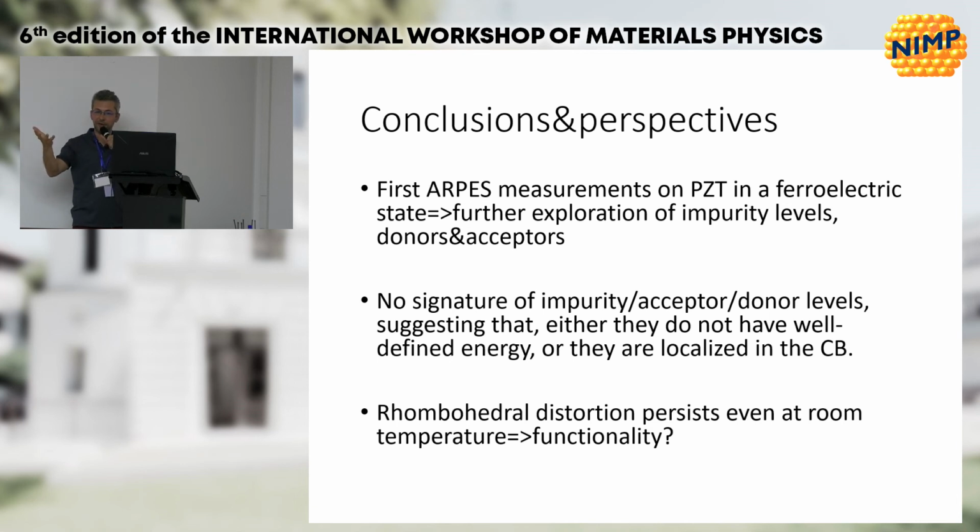Moreover, this rhombohedral distortion probably has some impact on the functionality. In PZT grown in a tetragonal lattice, the off-centering of the central atoms in order to define a well-defined ferroelectric state can occur only along the z-axis. On the other hand, in the rhombohedral phase, it will probably, at this level it is just speculation, occur more easily, but we'll see.